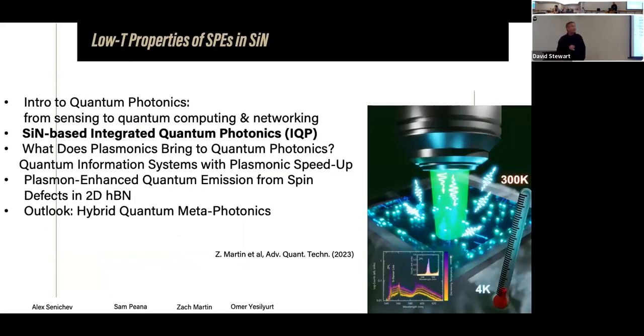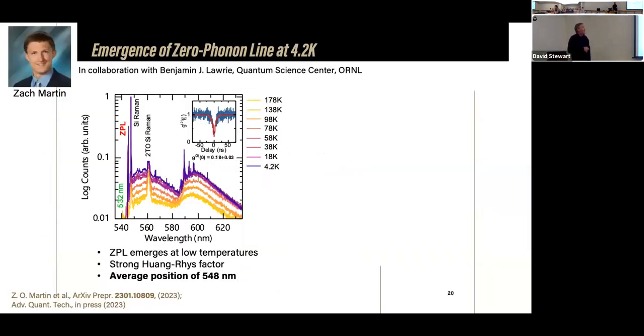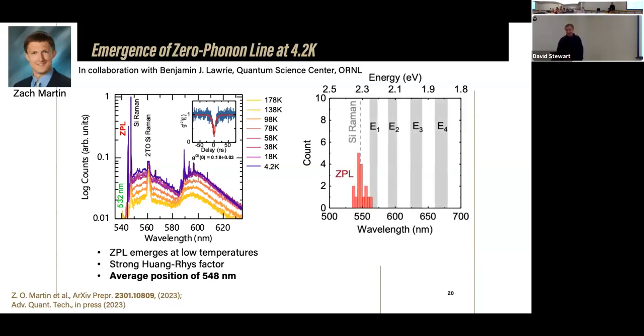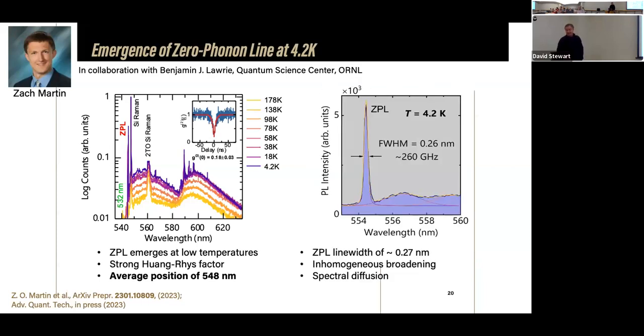So we of course started to look into the photophysical properties that were done by Zach, who spent some time at Oak Ridge National Lab doing these measurements as a function of temperature. And actually what was observed is that indeed we have this zero phonon line, which is close to the well-known silicon Raman line, and the position of the zero phonon line is around 550 nanometer. And of course, the real question is how broad it is.